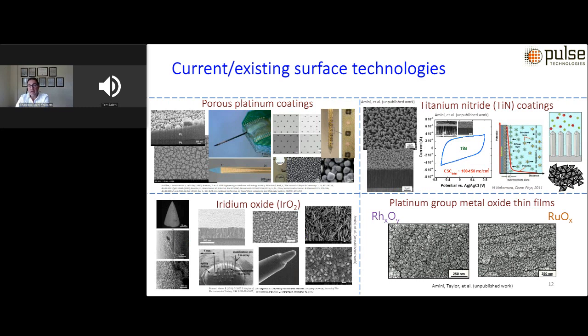Platinum black has been used for a number of years and is still being pursued. It is essentially a nanoporous platinum coating that has very high surface area and, as a result, high electrochemical performance, but it has very poor durability. Titanium nitride has been widely used. It is a chemically stable metallic conductor with excellent biocompatibility and excellent electrochemical performance, and has been used widely for many cardiac rhythm management devices.